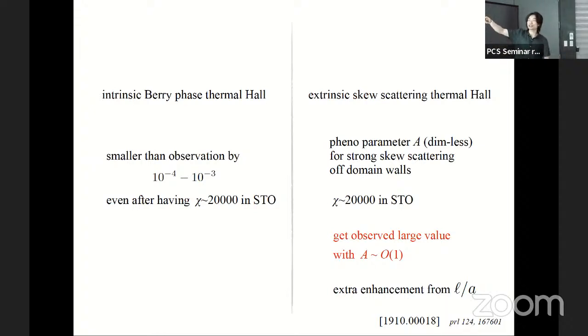And we find that indeed the extrinsic effect is about 10 to the 3 times larger than the intrinsic effect. And why is that? It turns out that it's because there's an extra enhancement from the mean free path over the lattice scale. So how do you relate this parameter to the magnetic field? Oh, it's because the phonons themselves have a large Berry curvature due to this large number. And with a large Berry curvature, when a strong scattering occurs, the skew component will also be strong. I see. So you combine the Berry curvature of phonon with a strong scattering. Right. So the large Berry curvature has this enhancement, and the skew scattering has this enhancement. With these two enhancements, we can explain the effect.